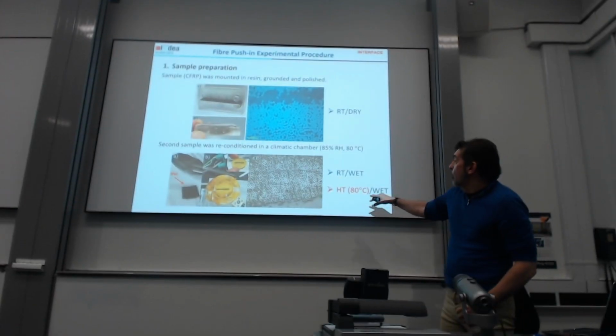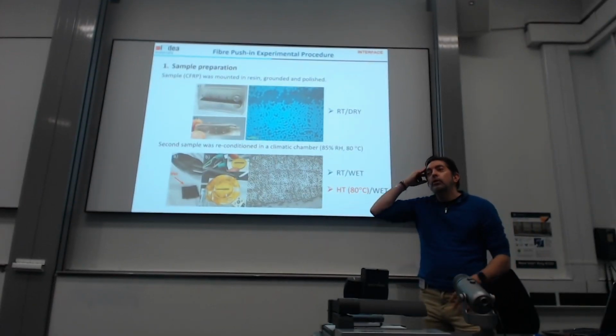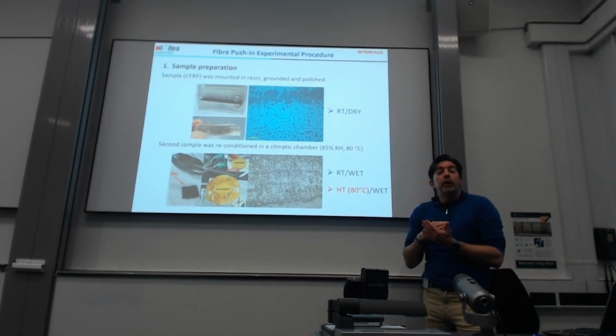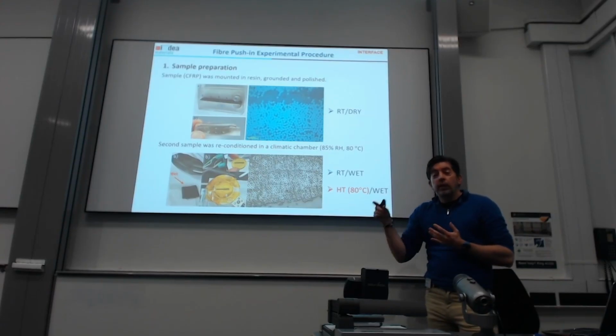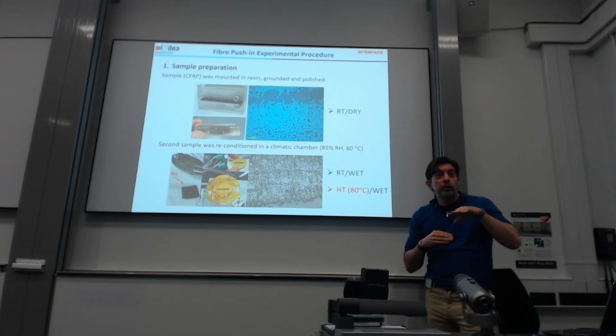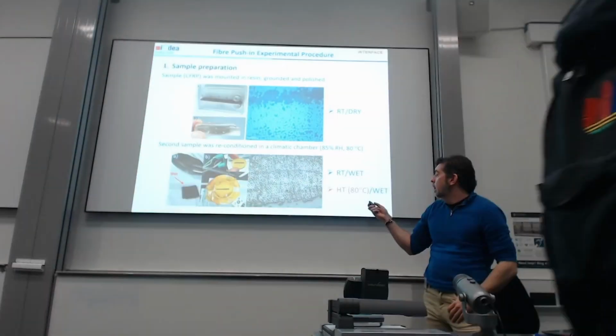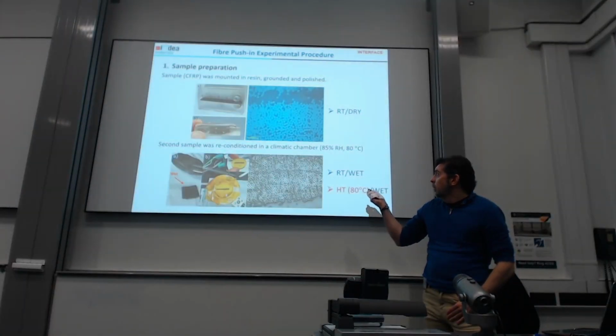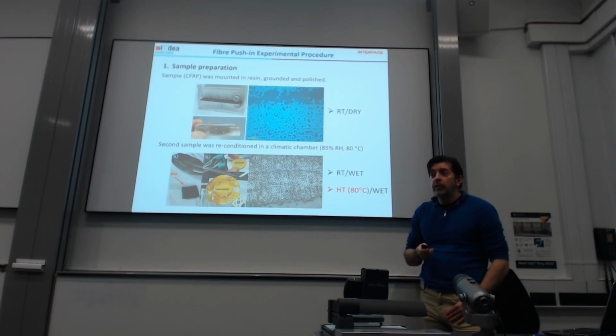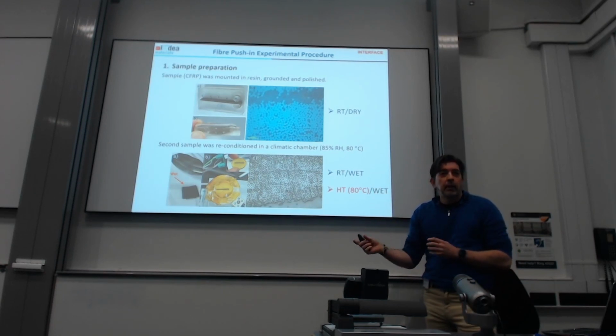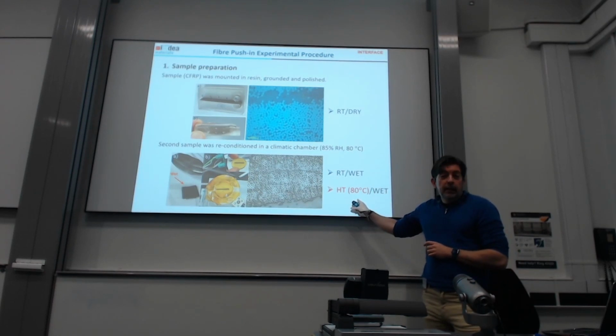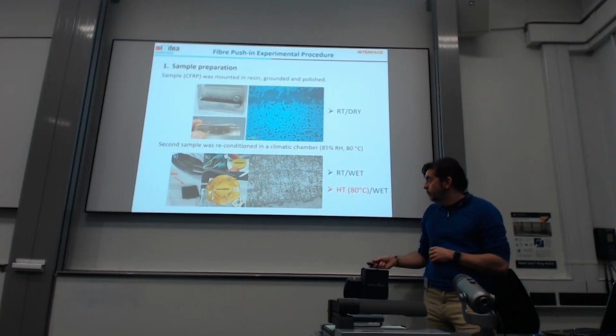For example, for wet conditions, sometimes we get the samples in a wet envelope, and we need to put them into the climatic chamber for many days to reach the water saturation level. So we put them in a climatic chamber with 85% relative humidity and 80 degrees, and then we test the material. And we also do the test at 80 degrees. That's the hot, wet condition.